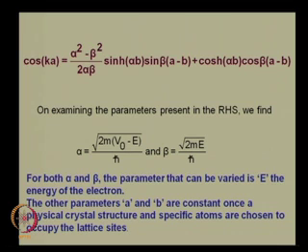Taking these conditions together, we have compared the value of the wave function at the origin as well as at a periodic boundary, and based on the periodic boundary requirement at two other locations, we compared both. We said that the solutions have to be reasonable, therefore the value of the function on either side of those locations has to be the same, and the value of the derivative on either side of those locations has to be the same. This gave us 4 equations, we attempted to solve those 4 equations and we found a very nice, interesting solution as a result of that process.